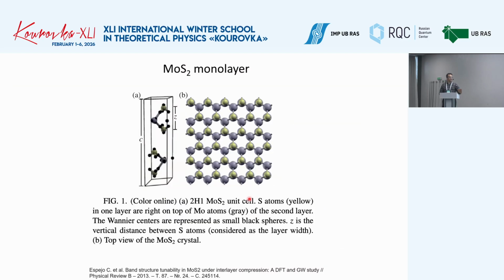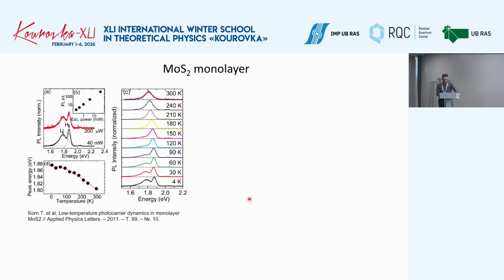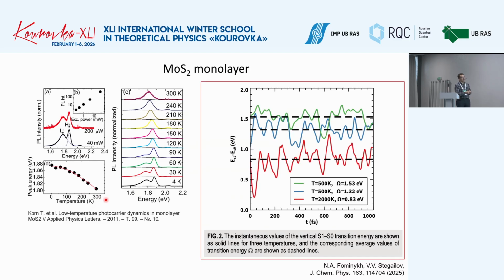And this is the MoS2 monolayer that is well known to everybody in this audience, of course. What we have calculated: long before, people measured how the peak energy of exciton depends on the temperature. Our calculations are for much higher temperatures, for 500 K, 1000 K, misprint here, and 2000 K. And our peak energies follow the same trend as in this experiment. So we observe nice correspondence of our quite simple DFT model and experimental data.